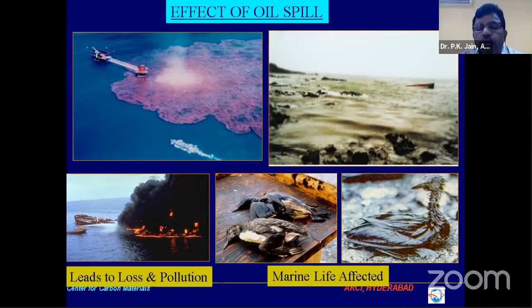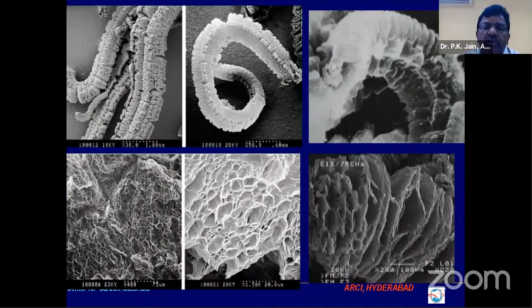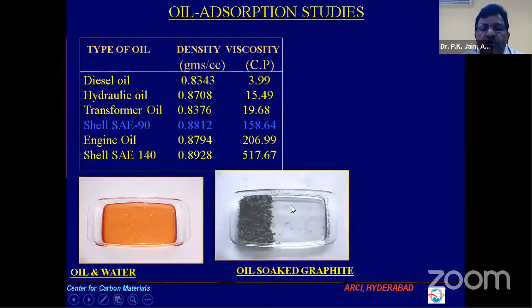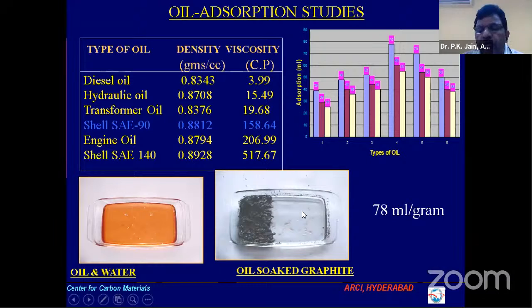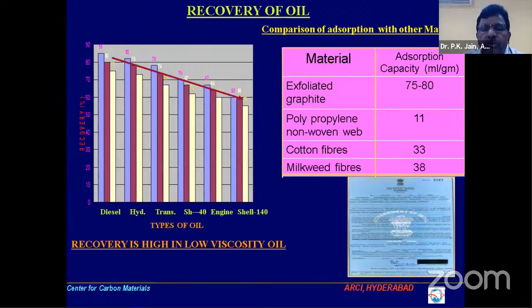So now this is another application of exfoliated graphite. There are oil spills, knowingly or unknowingly, whether in processing, or through terrorist attacks or accidents. Ultimately it affects many lives, marine life and tourism; everything gets affected. So we tried to study, using this expanded graphite, whether it can absorb the oil. And we found that it selectively absorbs only oil, no water. It can absorb around 78 to 80 ml per gram, and you can recover the oil back, and this is a very interesting activity.